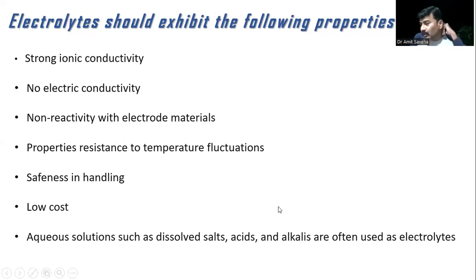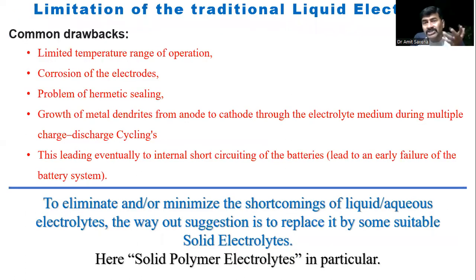So this is the traditional way of designing electrochemical devices, or you can say primary or secondary batteries, where we have one electrode, like anode and cathode, and we have liquid electrolyte in between them, because liquid electrolytes offer very good conductivity. But with traditional liquid electrolytes, there are many limitations, like the temperature range of operation, corrosion of electrodes, problem of hermetic sealing, growth of metal dendrites from anode to cathode through the electrolyte medium during multiple charging cycles, and this eventually leads to internal short circuit of the batteries.